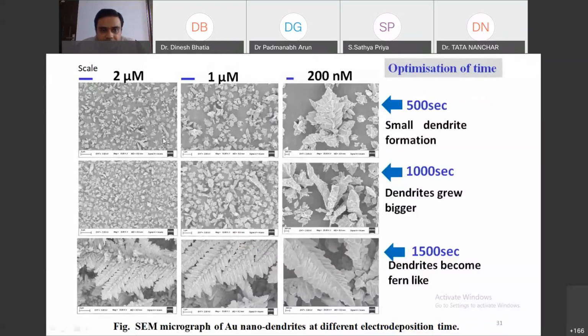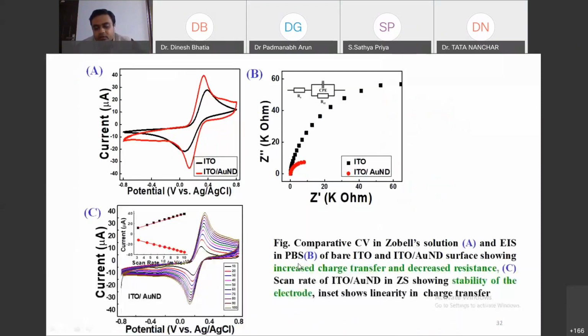So this is the surface. When we are creating a three-dimensional structure, we create for various time intervals, right? You can see from 500 to 1500 seconds, when we are increasing the time, the patterning is changing, and eventually this is the final optimized data. At 1500 seconds, this kind of pattern structure is forming, right? So after this process, we have to characterize the surface.